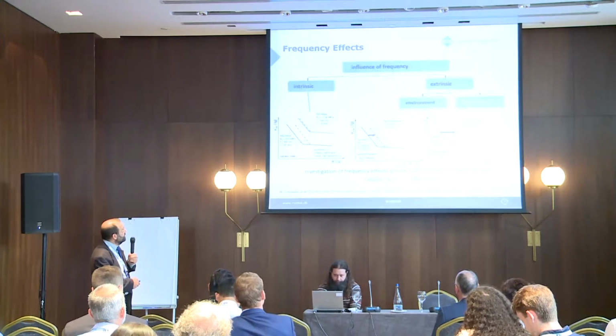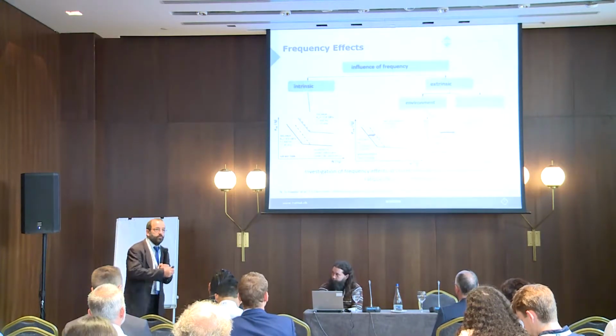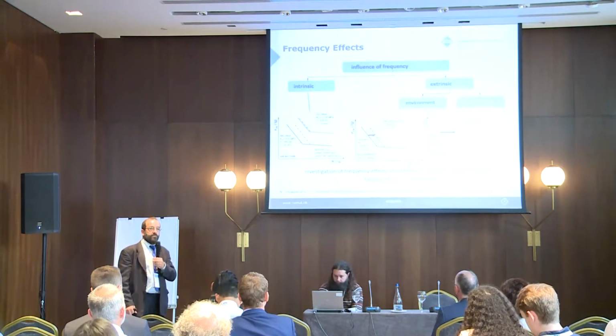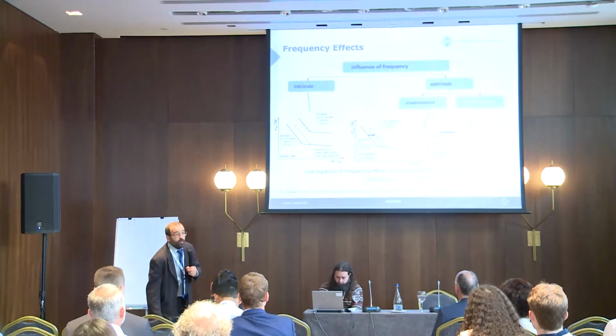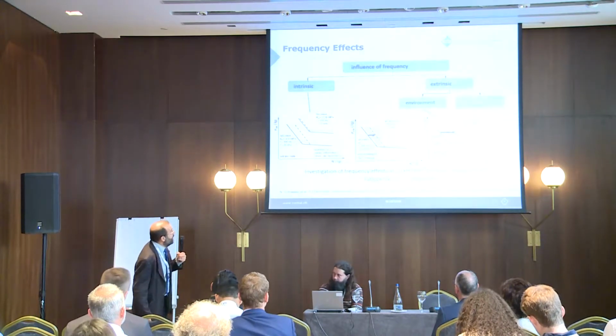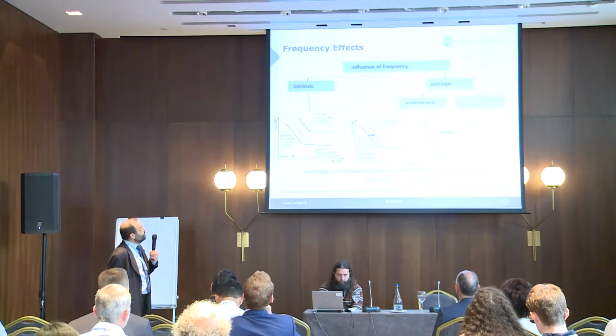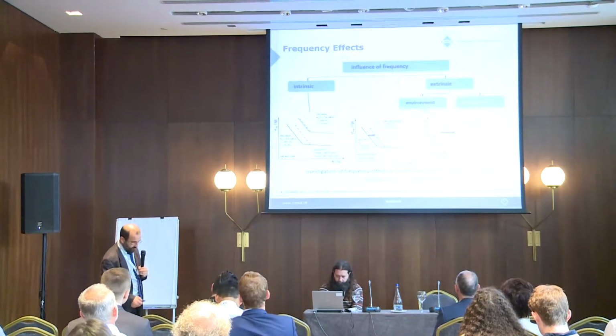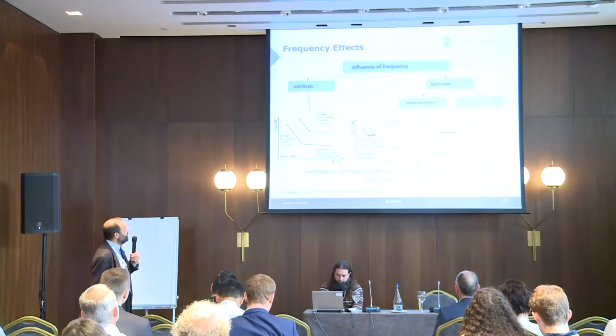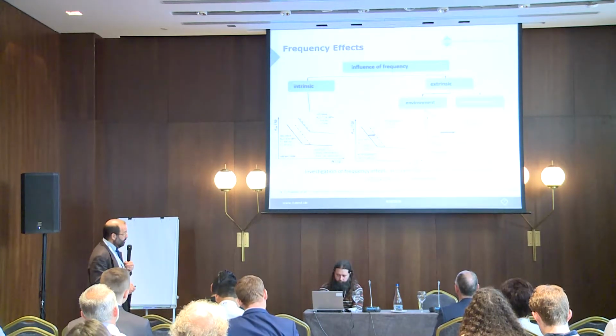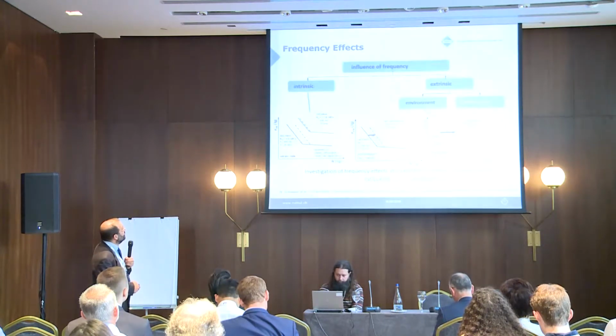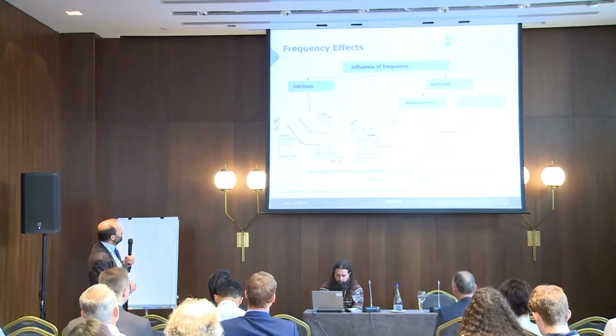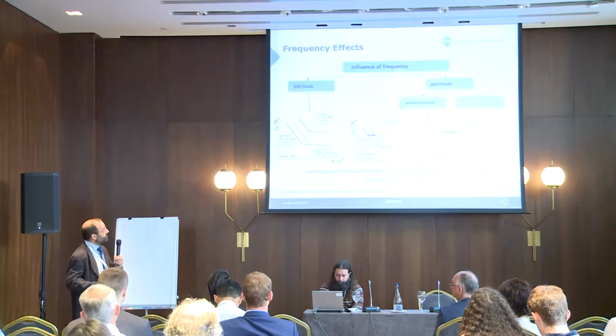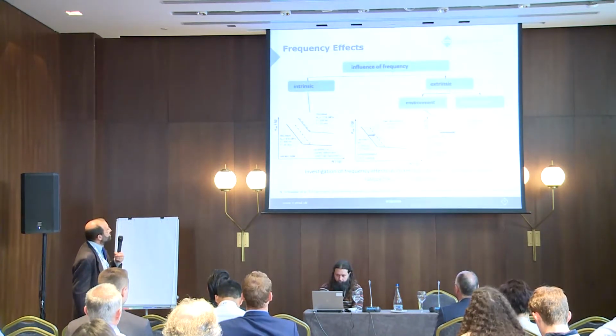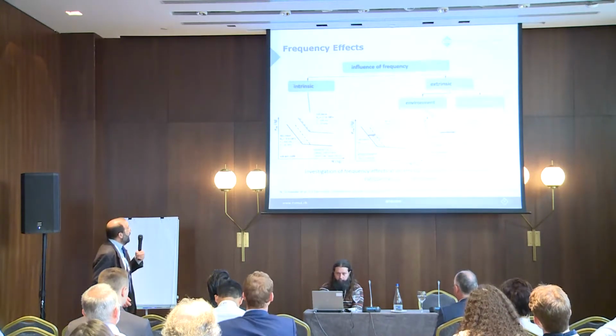Mr. Schneider from Technical University of Darmstadt could do it by using a 20 kilohertz ultrasonic testing system and a huge 400 hertz hydraulic testing system, and doing testing in inert atmosphere and normal environment in air. He found that on a martensitic steel in medium hard condition, he found a very big influence on fatigue life. The influence is bigger on the left side of the Wöhler curve than on the durability side.